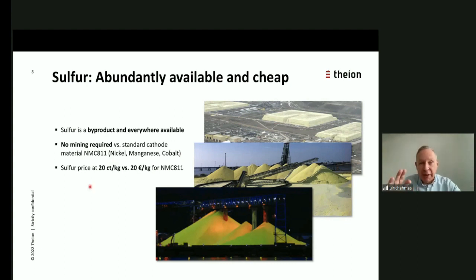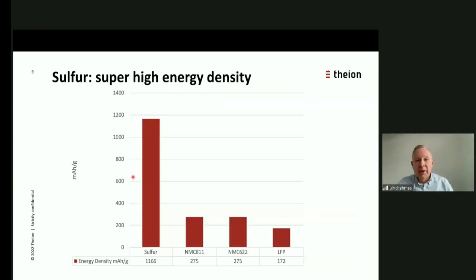And now from a cost perspective, it's even more interesting. Besides the availability, we pay only 20 cents per kg compared to 20 euros per kg for standard high energy density NMC cathode material. So we can say check on the cost side, remembering 50% of the material cost is cathode material. But there is another strong argument for sulfur. This is the super high energy density, measured in milliampere hours per gram. If we compare that to iron phosphate or the NMC cathode materials, we are far beyond 1,000 milliampere hours per gram. So abundantly available, cheap, high energy density.